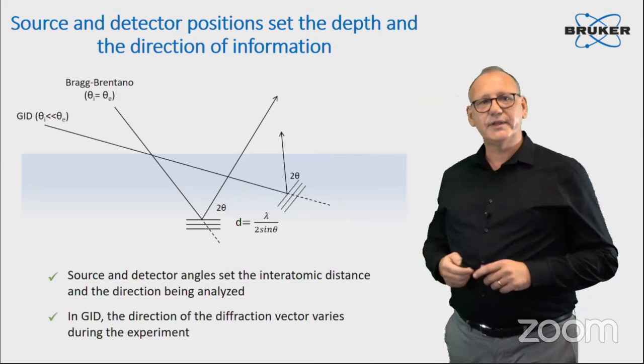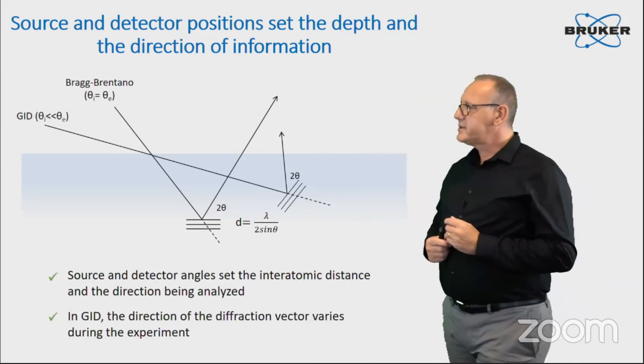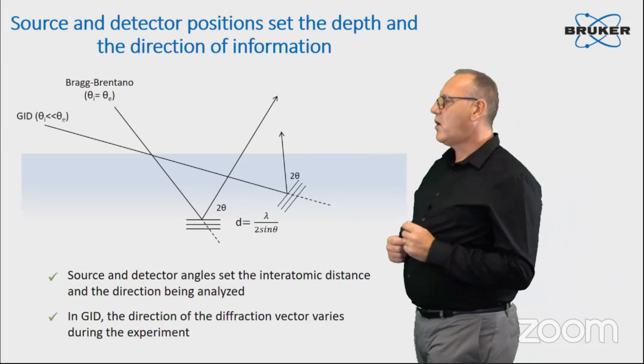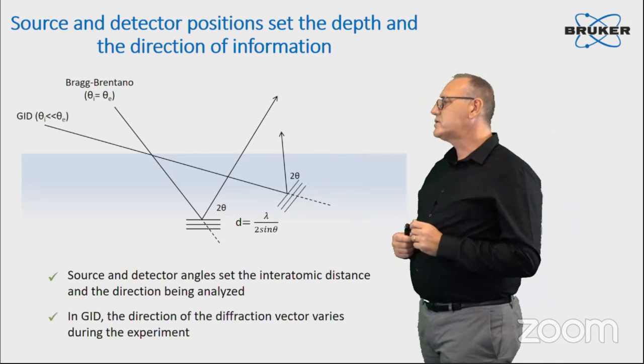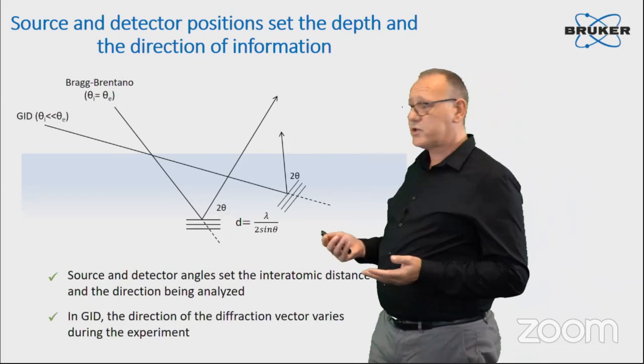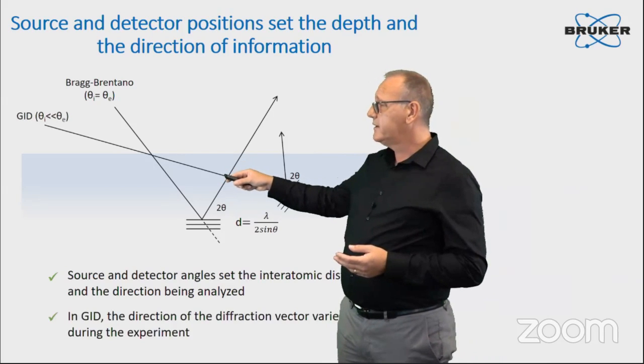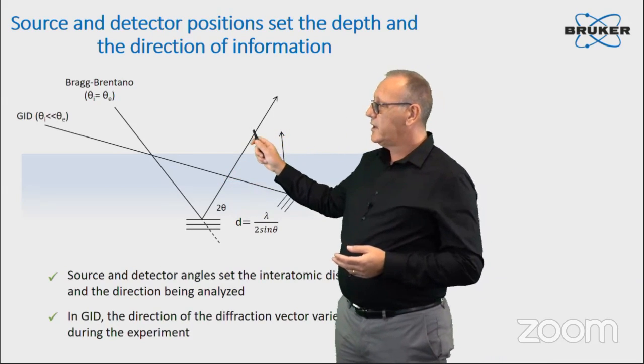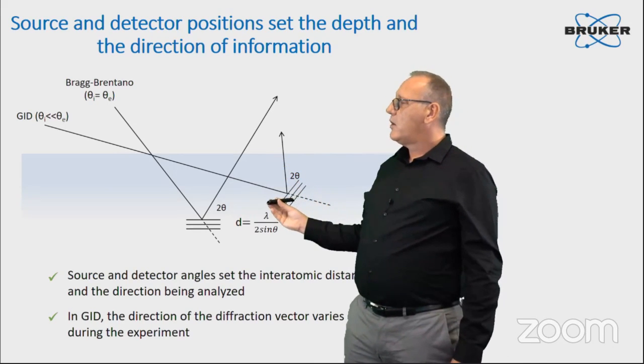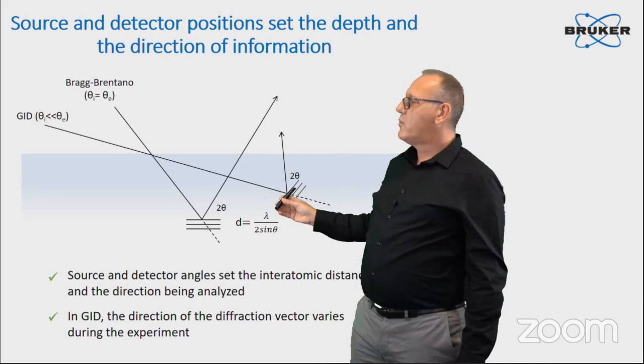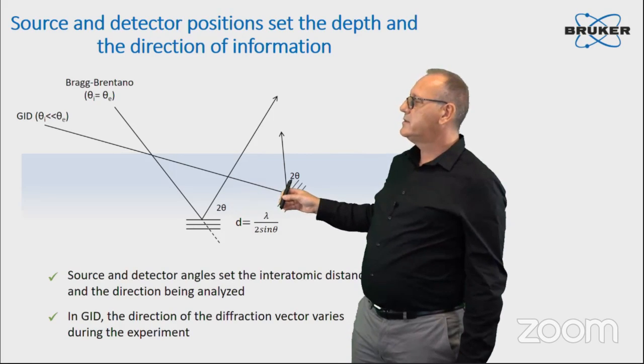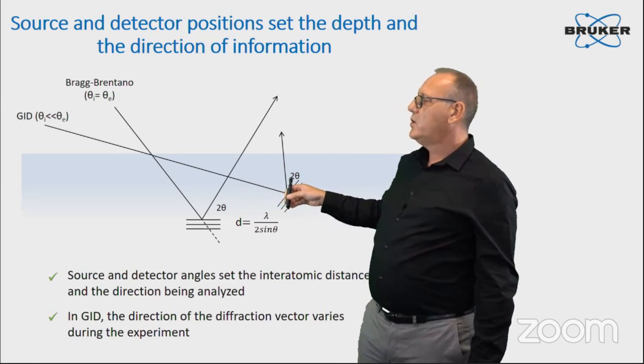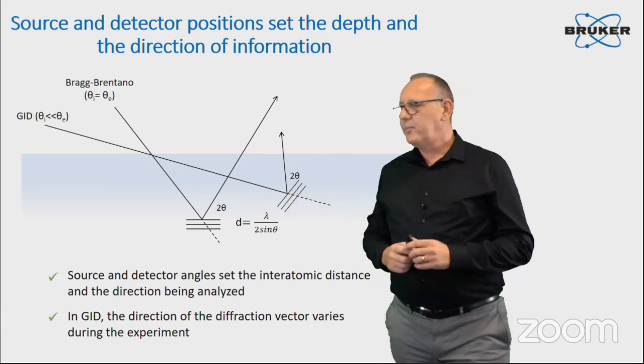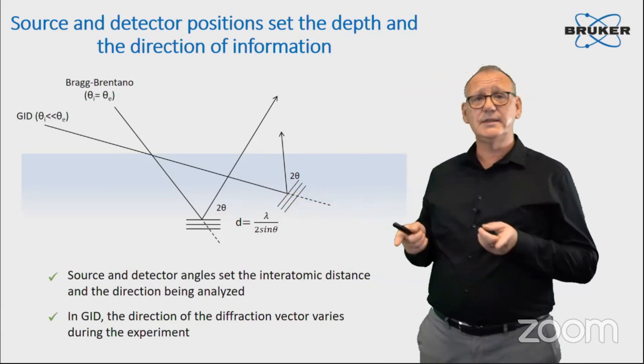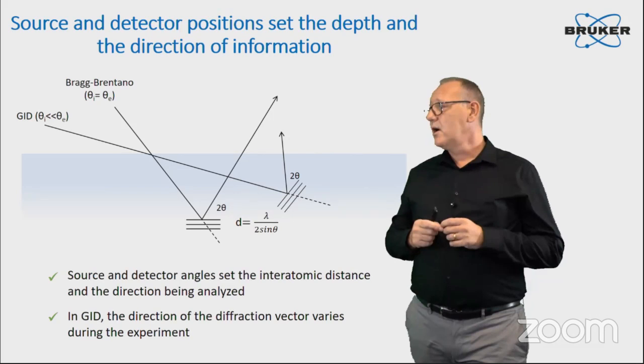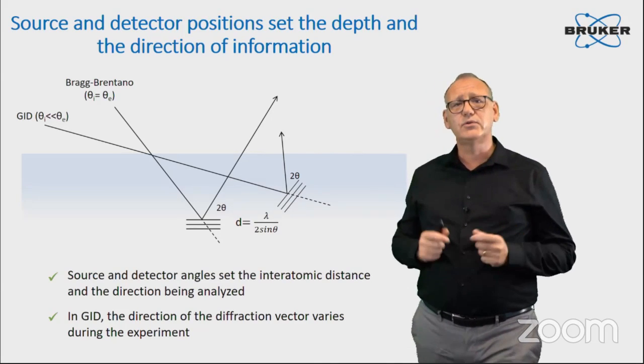This is pretty different in GID. In grazing incidence diffraction, the direction of the diffraction vector varies permanently during the measurement. Your incident beam is fixed, your detector is moving. So that means that the higher the 2 theta you go, the more inclined is the grain. So you have a variation of the plane inclination you are investigating, and we will see that this will be a very big advantage for residual stress evaluation in your material.